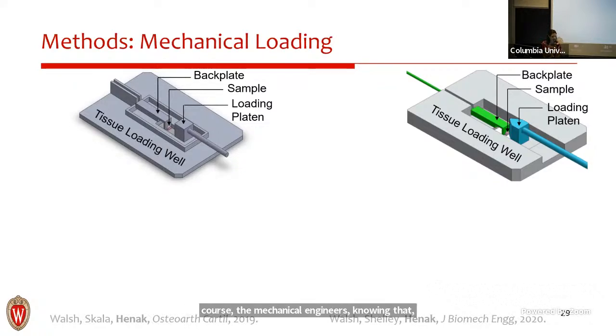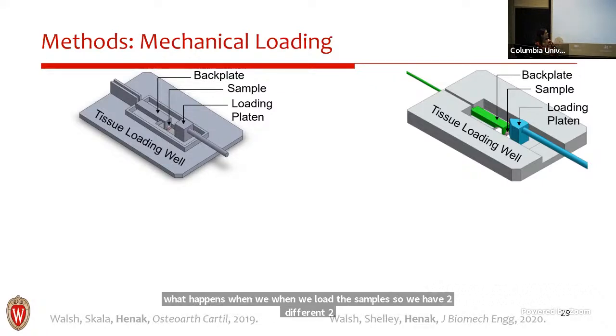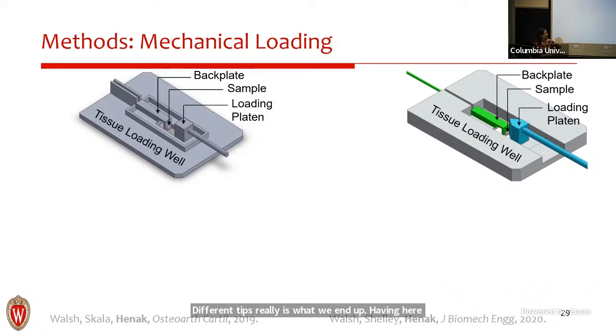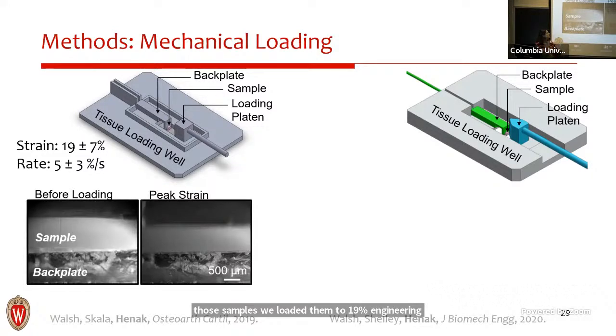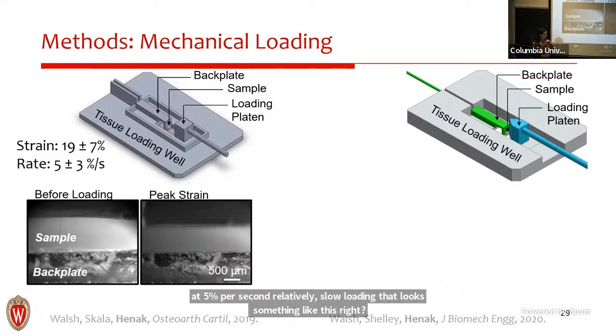So we have two different tips, really, is what we end up having here. Both of these setups sit on top of an inverted microscope, and they have this deformable backplate so that we can watch the cartilage sample while it is loaded, estimate the forces applied, calculate the bulk strain, and then we load it with 2 different platens. So on the left, what we have is just a flat platen. So this applies the load over the whole sample. And for those samples, we loaded them to 19% engineering strain at 5% per second, relatively slow loading. And that looks something like this, right? So we've got that compression across the whole sample.